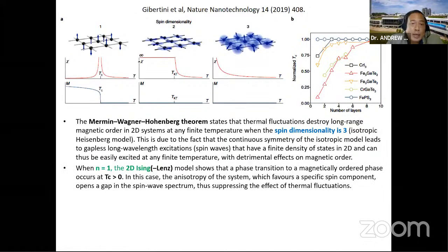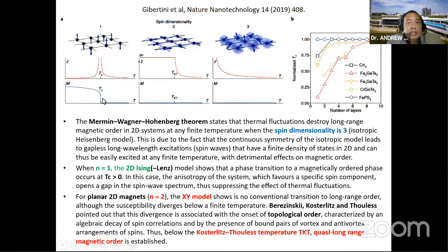But when n is 1, the opposite extreme where the spin can only be up or down, you have what is known as the Ising model. In this case, because of the intrinsic anisotropy of this system, this opens up a gap in what is known as the spin wave spectrum, which suppresses the effect of thermal fluctuations. So in this case, it is possible to get a transition temperature, the Curie temperature here. And in the intermediate case for the planar or 2D magnets, what is known as the XY model,